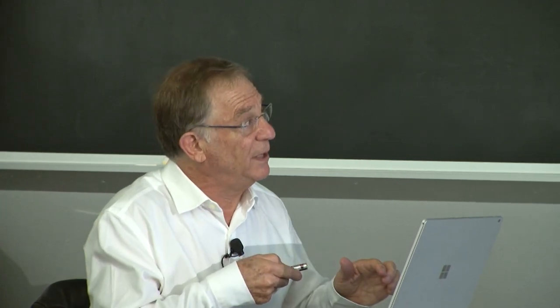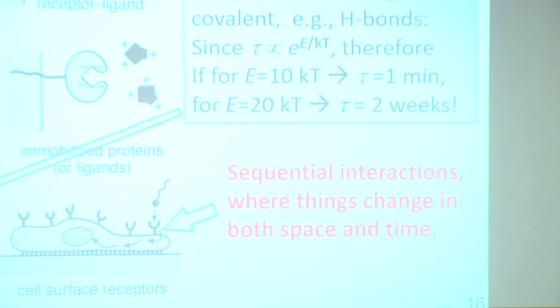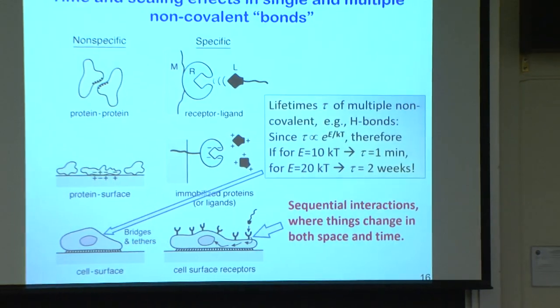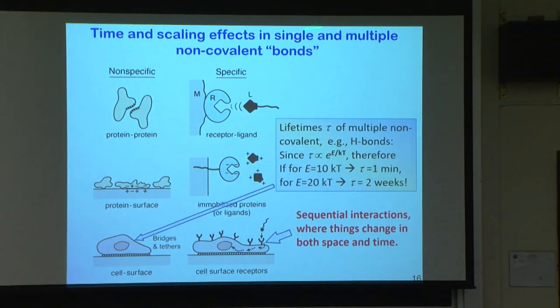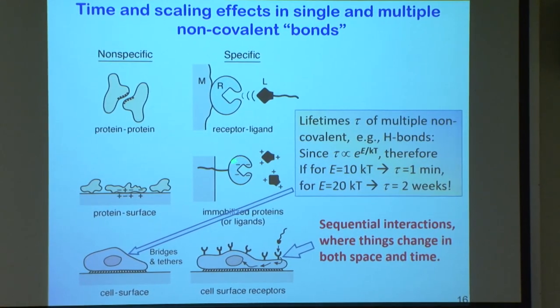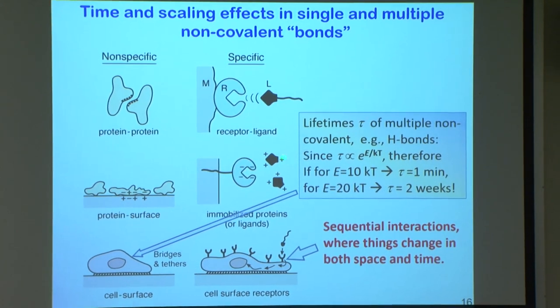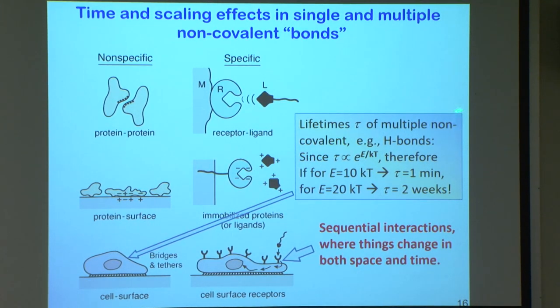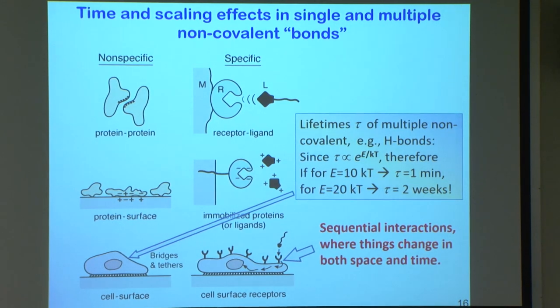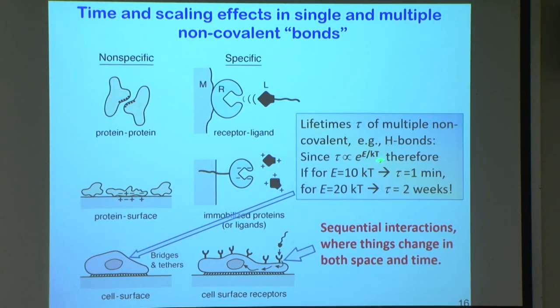So here we have adhesion, but if you look in detail, you see both material transfer and what's known as stick-slip motion. Now, with biological systems at the molecular level, we have lots of interactions that can be time dependent. The only thing I want to point out is that the lifetime of a bond depends on the energy, with some characteristic rate, which is the vibration rate of the molecules, multiplied by e to the power of E over kT.